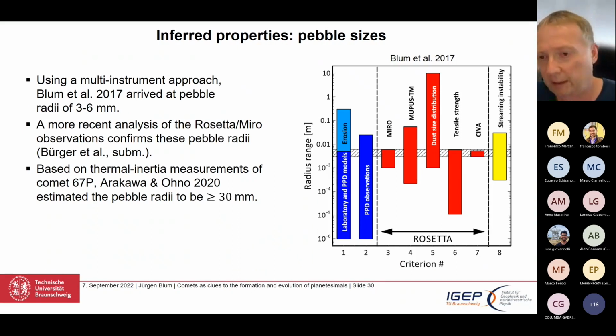However, there has been more work on the properties of comets that are made up of pebbles. So we studied the pebble sizes back in 2017. We analyzed many instruments, ground-based observations, and theoretical attempts to understand the formation of planetesimals, and ended up at plausible pebble radii between 3 and 6 millimeters. A recent submission of my group confirms these results with more detailed analyses. However, there's other work by Japanese colleagues who claim from thermal inertia measurements, also thermal measurements as we do, that the pebbles must be bigger than 3 centimeters. You see, there is still room for play here, but it's certain that if the pebbles are present, they are on the order of 1 centimeter or so.